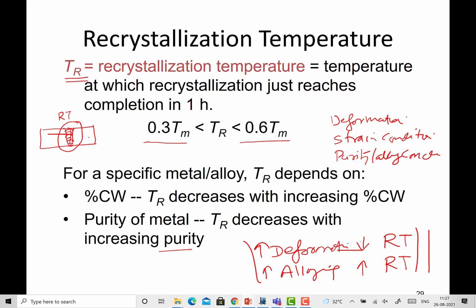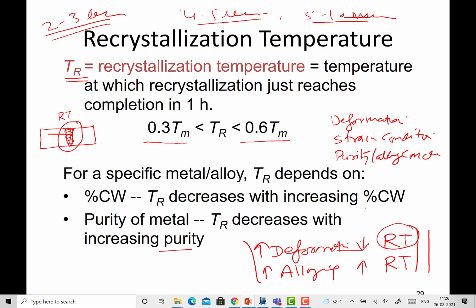Even diffusion bonding will be experiencing micro level interfacial deformation, which may range from 2 to 3 micrometer. In your ultrasonic welding it may be like 4 to 5 micrometer on both sides, and in friction stir welding maybe 5 to 10 mm of the weld nugget zone. So the metal is being deformed heavily to different magnitudes or different levels. And this deformation will be lowering the recrystallization temperature, and thereby it will be affecting the properties.